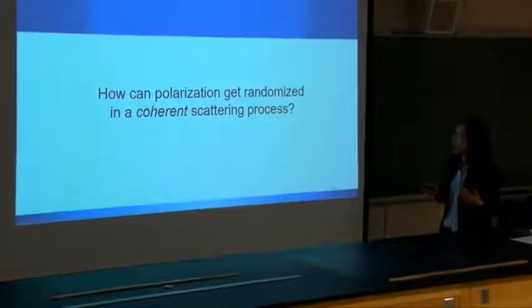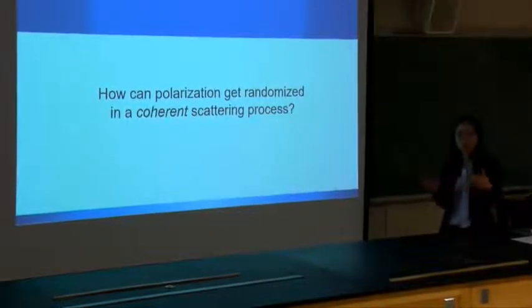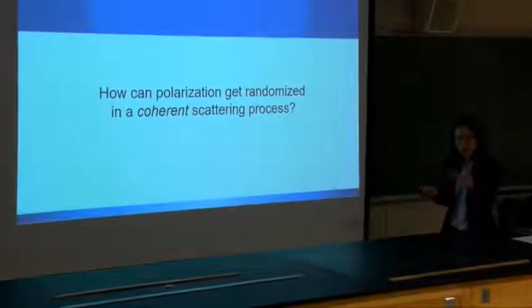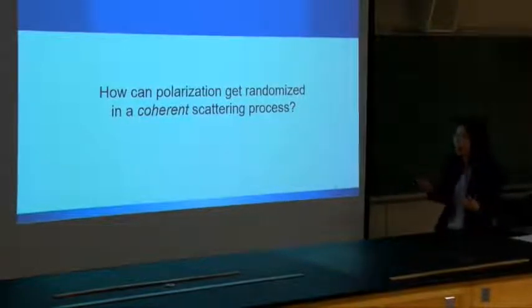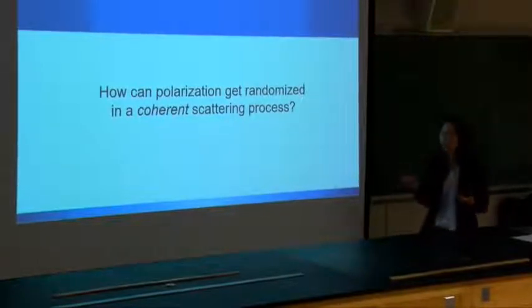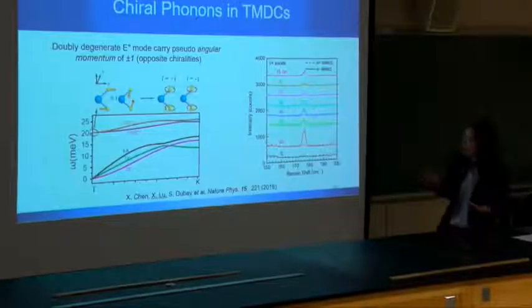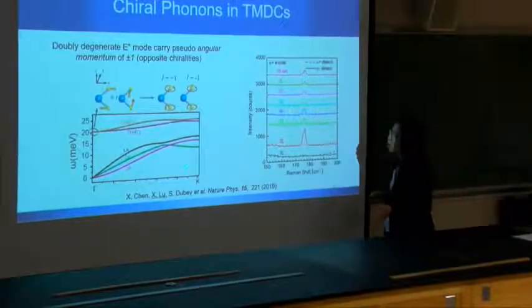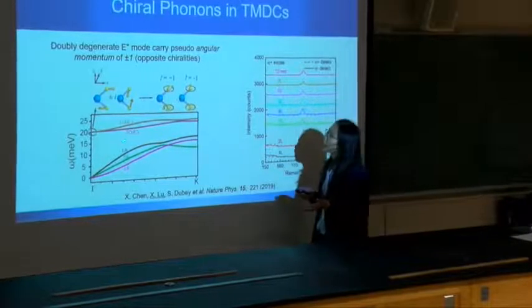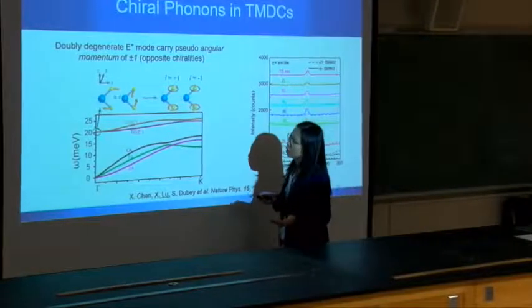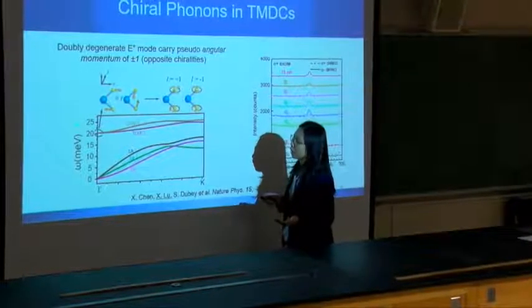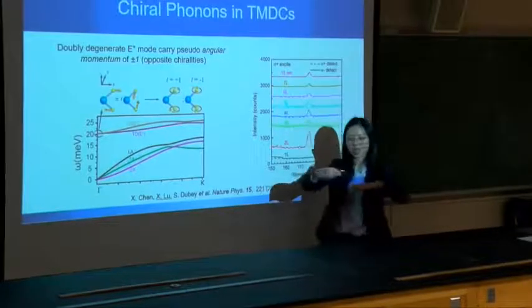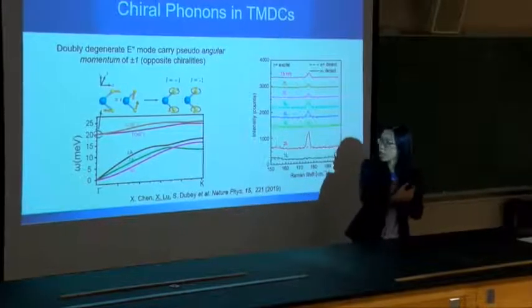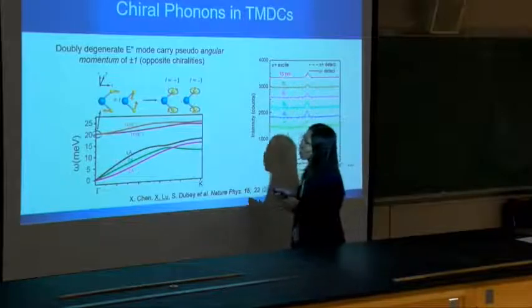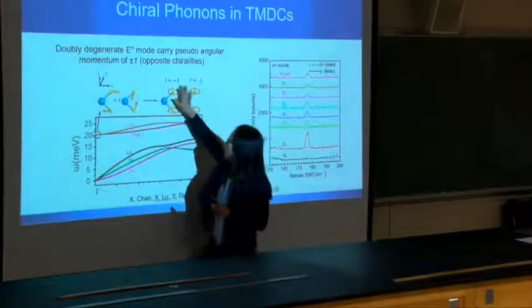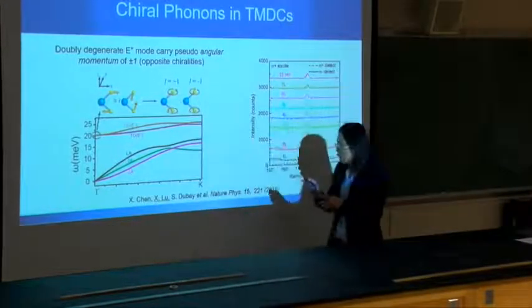But how can a coherent Raman scattering process lose the information of the polarization? That doesn't sound reasonable. So we go back to the phonon itself, maybe something weird there. So the phonon, as I just mentioned, is a doubly degenerate phonon at the gamma point. We can consider x direction or y direction. And in principle, it can superpose to become a chiral phonon.